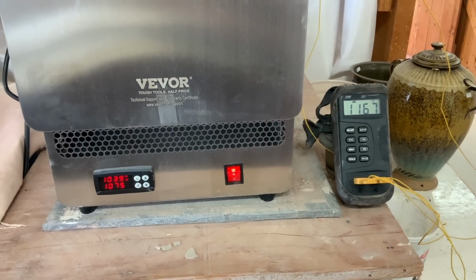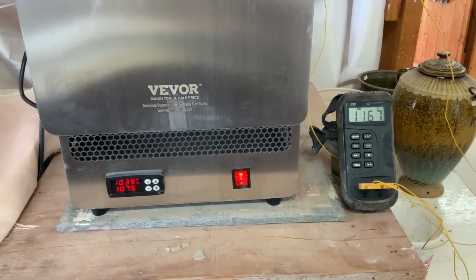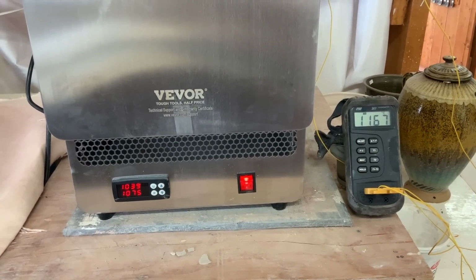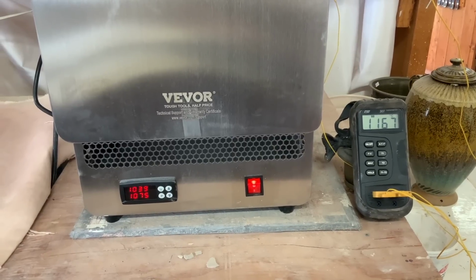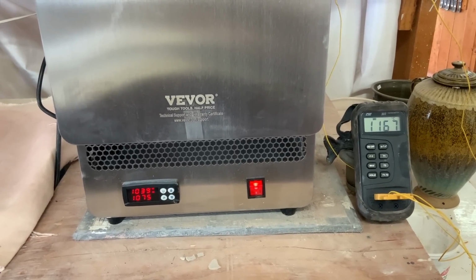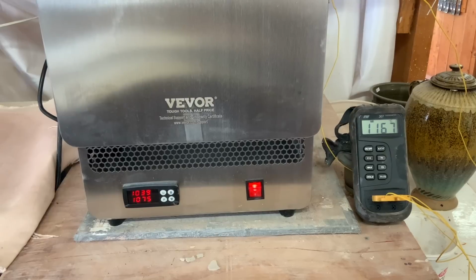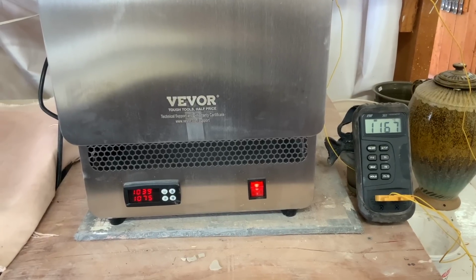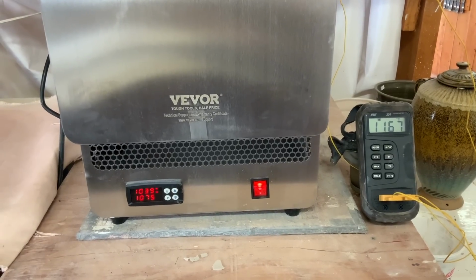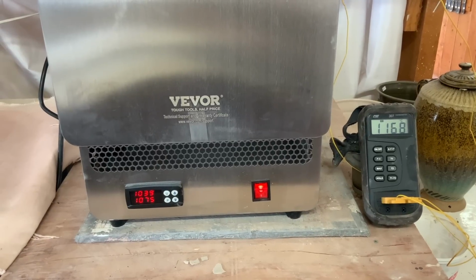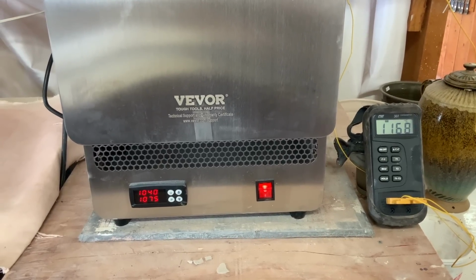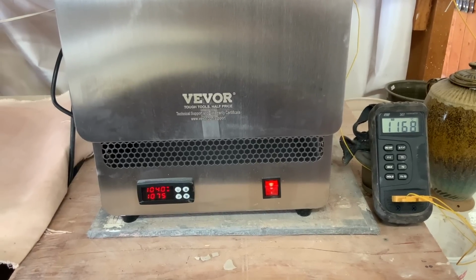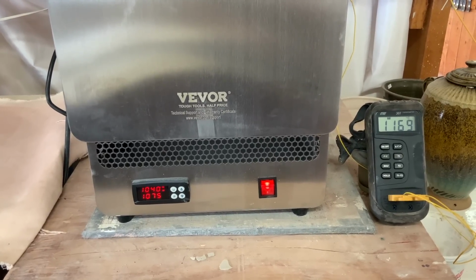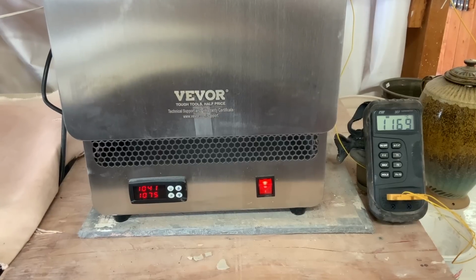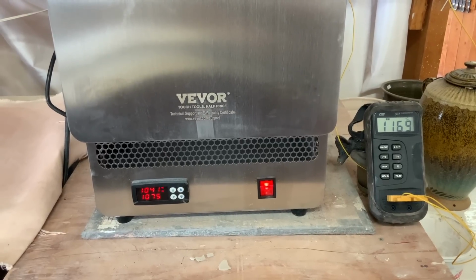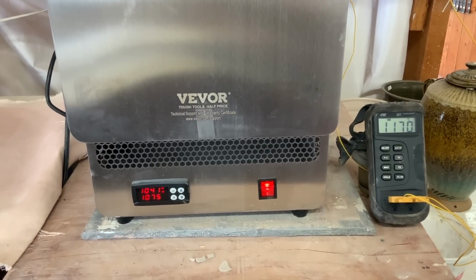Okay, I pressed P first to stop it, and then I pressed the U button to lower the temperature by 25 degrees on the kiln, because we are really close. So now the difference between the two, 50 degrees and 33 degrees on my pyrometer, I'm hoping to even it out around 1200, and then I'm going to slowly increase it a little bit to about maybe 1225 on my pyrometer, because that's the temperature my Bailey kilns that I actually fire to, 1225.